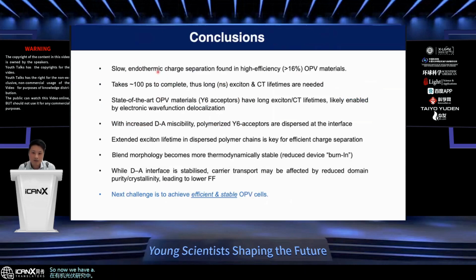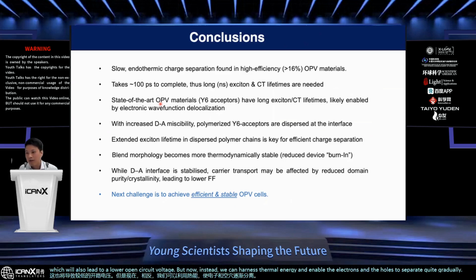So now we have an understanding of how the charges separate, the time scale, and whether or not temperature matters. They are very different to the traditional fullerene types. We no longer need to physically pull apart the electron from the hole on an ultra-fast time scale, which will also lead to a lower open circuit voltage. But now instead we can harness thermal energy and enable the electrons and the holes to separate quite gradually, slowly but gradually, but without needing to lose any energy at the interface.